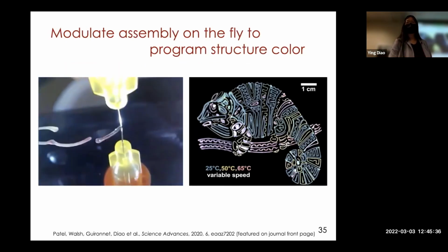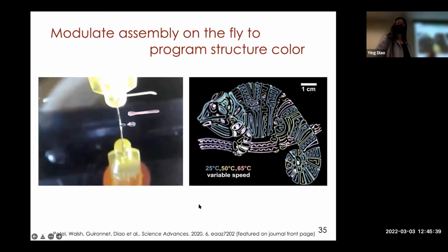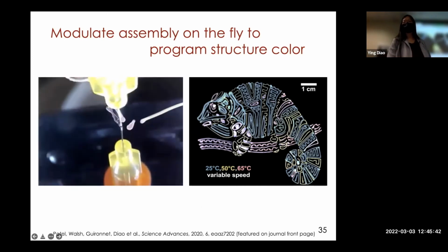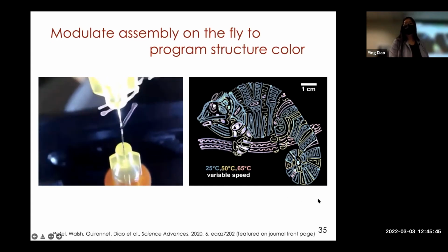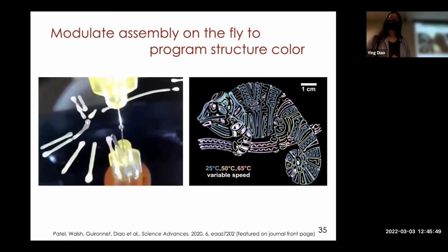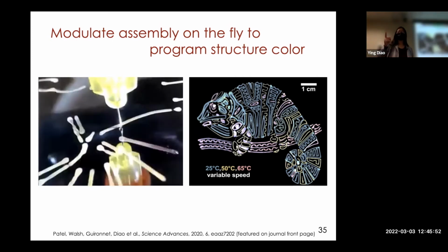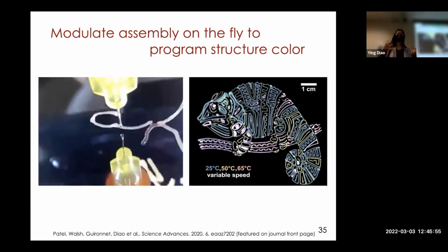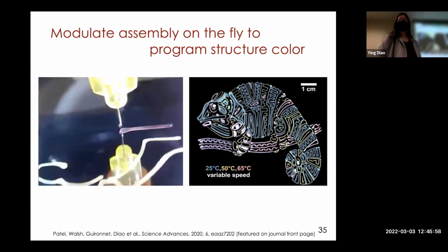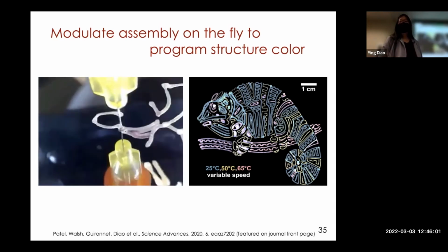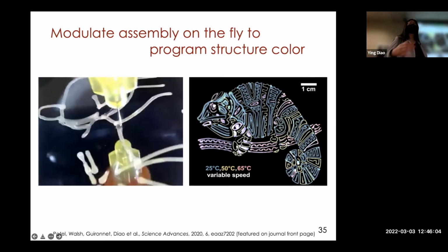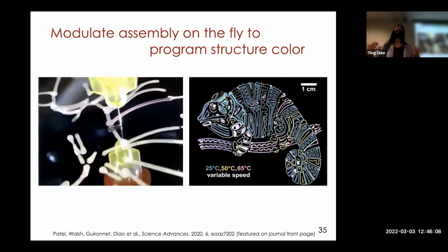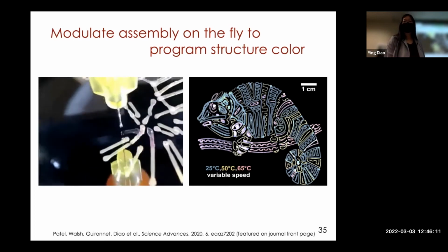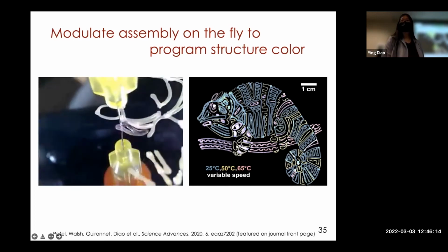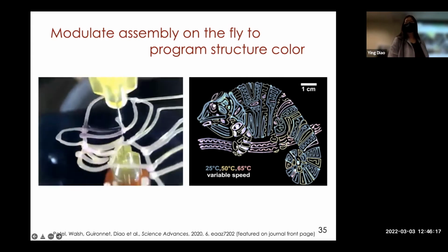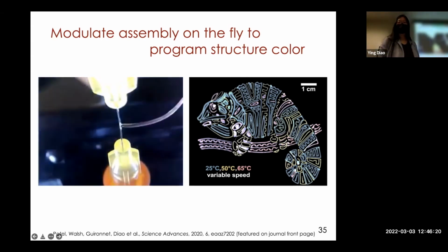And with this insight, we simply program the printing process and we made these colorful prints without changing the ink materials. So imagine that you have one single pigment and then you shuffle it into the printer and then it can create a colorful image without you having to change the structure of the ink or the composition. So that's the power of understanding how printing tunes assembly: it can give us dynamic on-the-fly control. And in fact, this chameleon showed up in two French children's magazines that flew all over the globe when we published the paper.